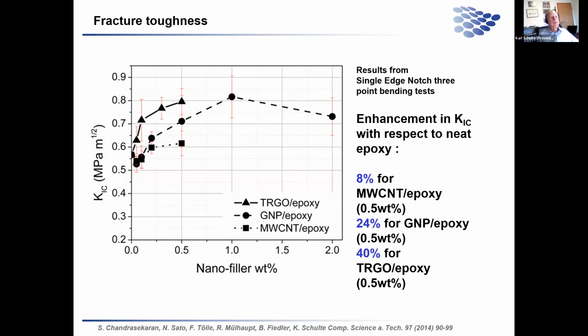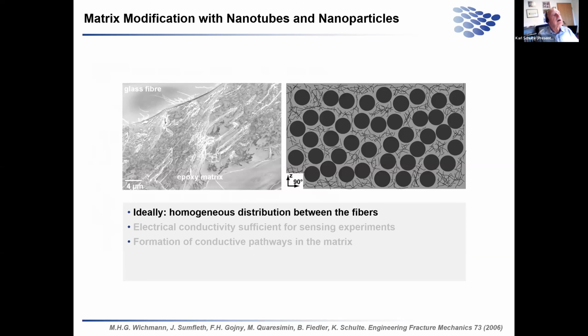With only about 0.5% of the fillers, we see an increase in the fracture toughness of up to 40%. So this increase in the matrix properties should also result in improved properties in a fiber reinforced epoxy.